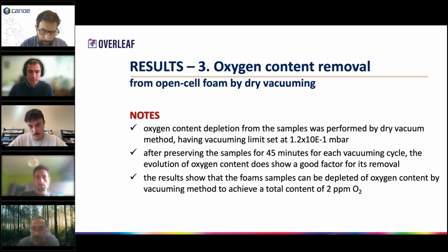levels. Regarding the oxygen content removal by dry vacuuming and rough vacuuming, we need to pinpoint the limitations, especially the value of the vacuum, 10 to the minus 1 millibars. It can be seen that the evolution of oxygen content does show a good factor of removal, especially for this type of material, insulation foams. It means that at this value, the forces that keep the oxygen in the structure are not very strong.